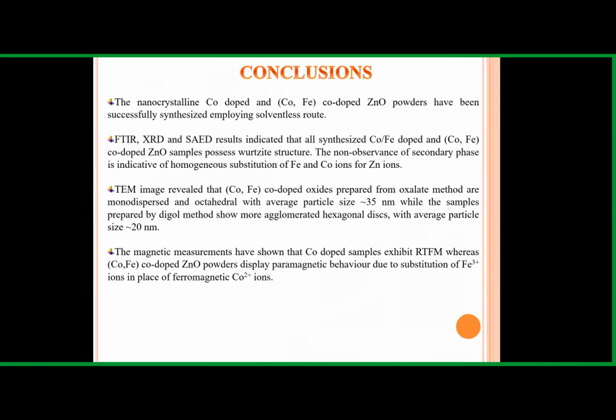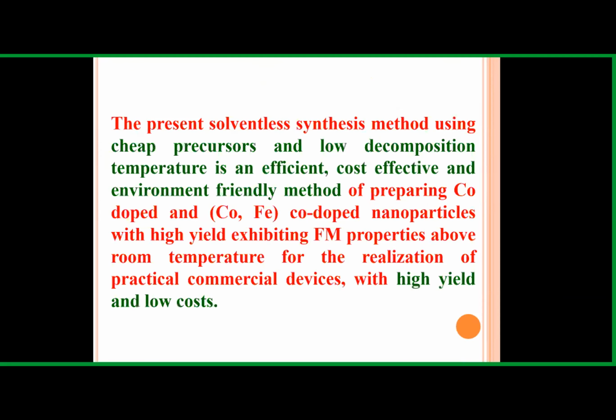So in conclusion, we just wanted to compare two strategic methods for the preparation of cobalt, iron doped and co-doped zinc oxide nanoparticles. We have seen from the characterization, the FTIR, XRD and all these results, that the zinc oxide nanoparticles prepared after doping and co-doping are free from any impurity. There is no iron oxide or cobalt oxide impurity in the prepared nanoparticles.